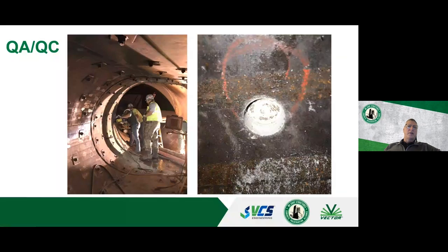The QA/QC after was, again, running impact echo, trying to find voids. They would identify where there were spots, and we would use a mag drill and drill through. You can see we pretty much had 100% success, because once you got through the steel, you could see the complete circumference of that hole on the right-hand side has been grouted and filled.